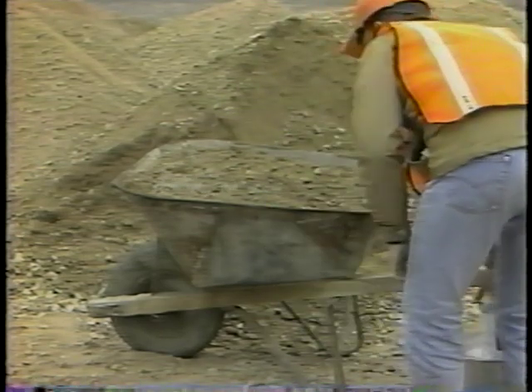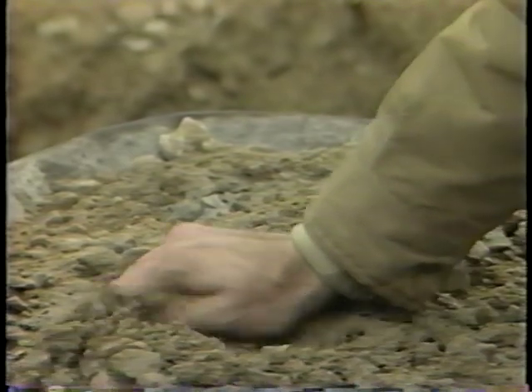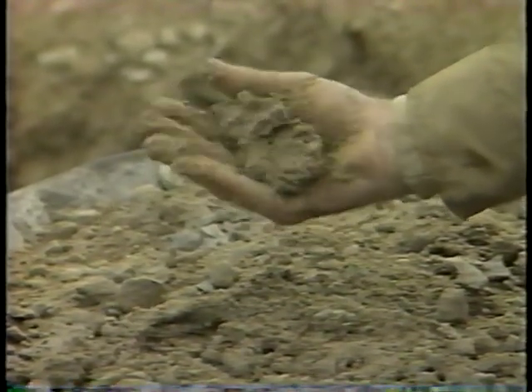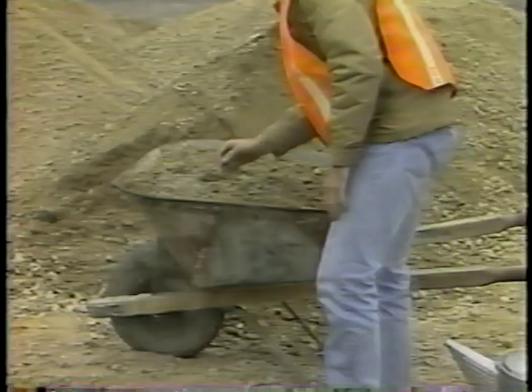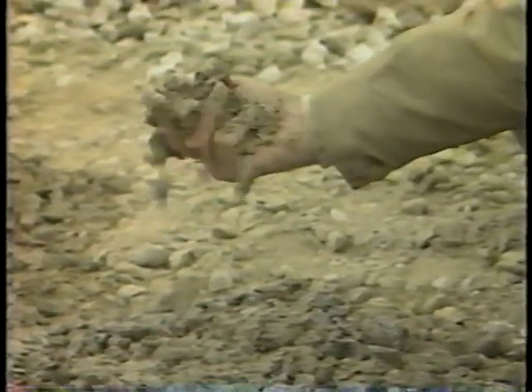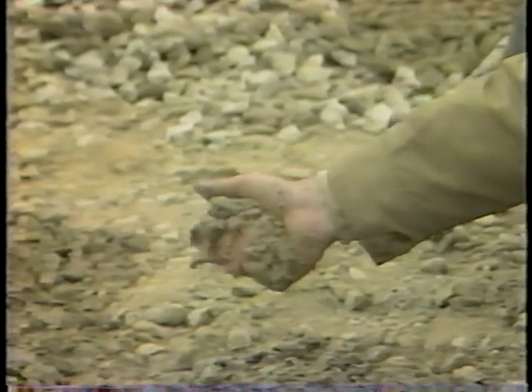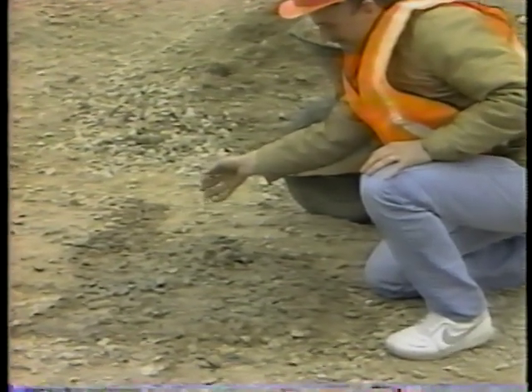A sample has correct moisture if it forms a tight, compact ball when you squeeze it. If the sample is too wet, it will flow very slowly between your fingers when you squeeze it. In this case, the granular material should be spread out to dry.